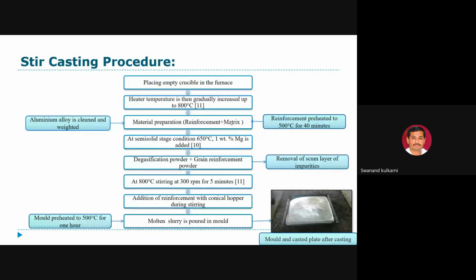Suppose at 650 degrees centigrade, sometimes magnesium is also added. The purpose of adding magnesium is to improve the wettability, because if wettability is proper, then bonding between matrix and reinforcement is better. Unless wettability is ensured, bonding is not achieved. So magnesium at 1% is added, and at the same time degasification powder and grain refinement powder are also added. Degasification powders are added to remove entrapped gases, or if any oxide layer is generated on the surfaces, the degasification tablets are useful.